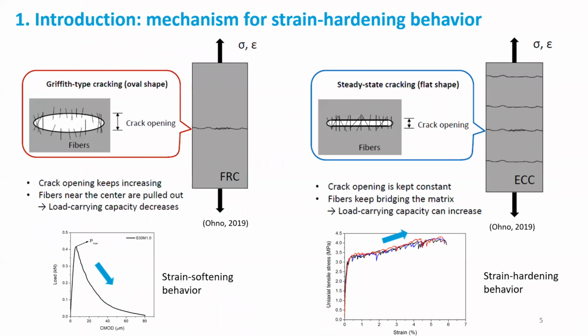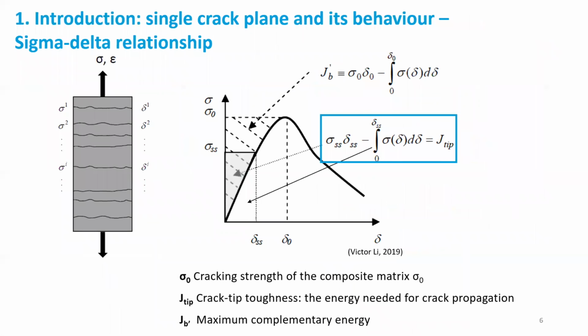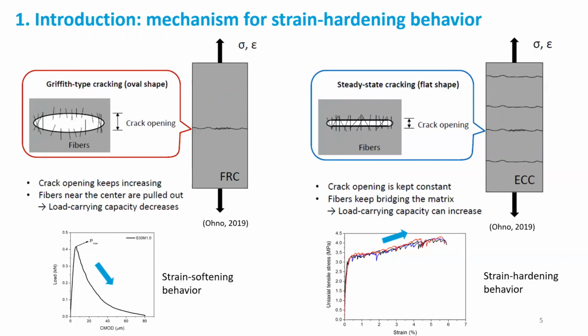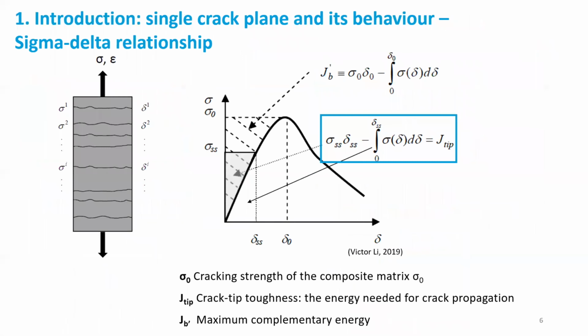Before we go deep into the presentation, I would like to make a very brief introduction to the mechanism for strain hardening behavior to happen. The most important thing for strain hardening behavior is steady-state cracking of the composite under tension. Otherwise, you will have a Griffith-type crack, which finally leads to strain softening behavior of your mixture. This is what normally happens with conventional concrete and also conventional fiber reinforced concrete.